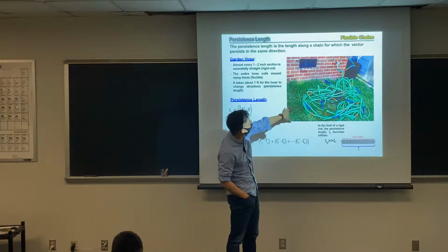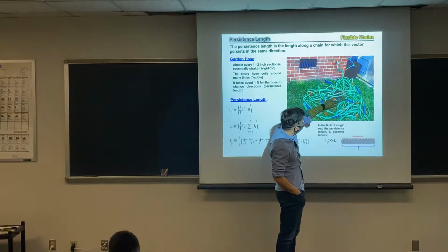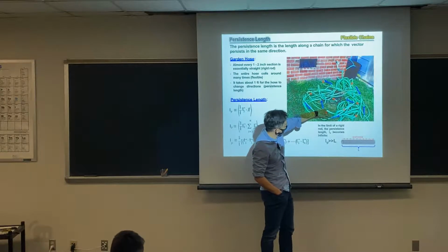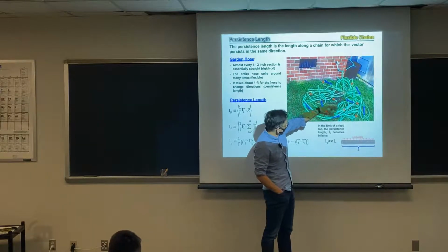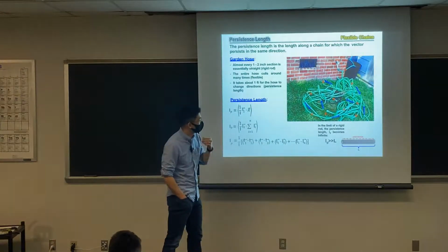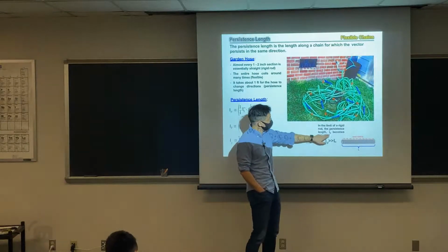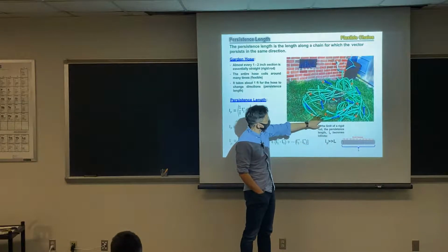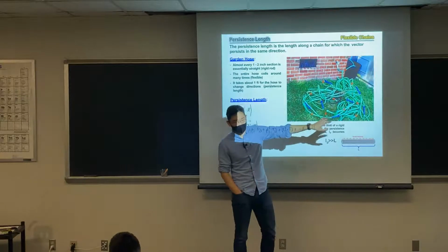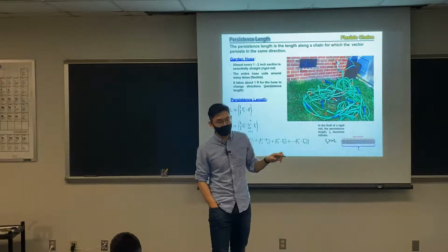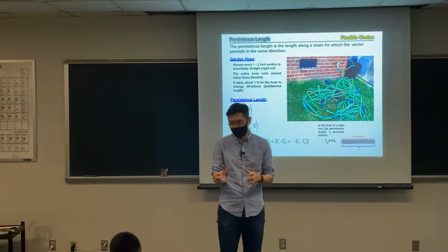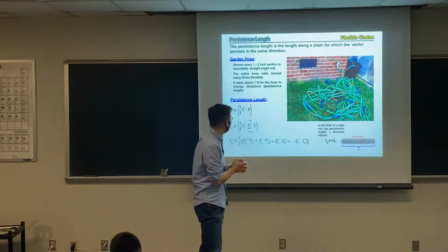At a very, very small scale, let's say within this length, it behaves like a pretty rigid rod. And on a larger scale, it will become flexible. So we just need to measure this L P value, then understand what length scale you are comparing with L P. If your length scale is smaller than L P, it behaves like a rigid rod. If your length scale is much bigger, then it's flexible.